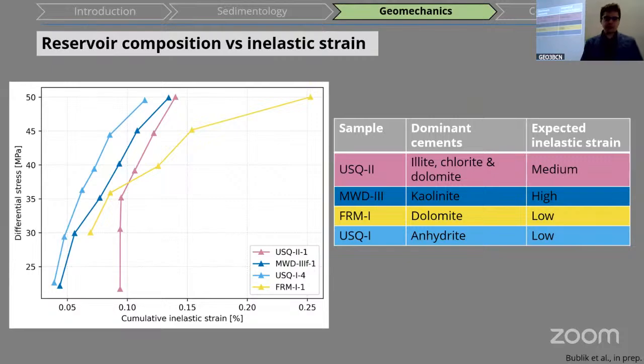But what you can see is that this yellow one is very different. We expected this should be low deformation, but we actually see very high deformation. And that's, of course, not what we expected, which makes it very interesting, because whenever there's something which you don't expect, it's quite fun to figure it out.